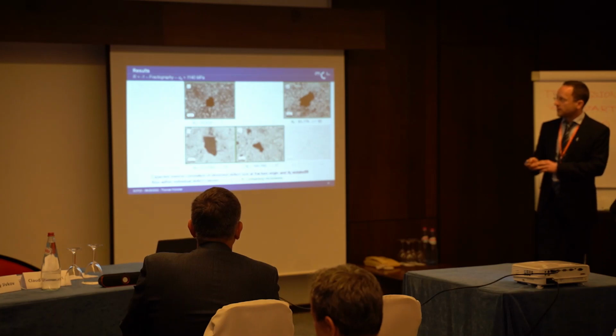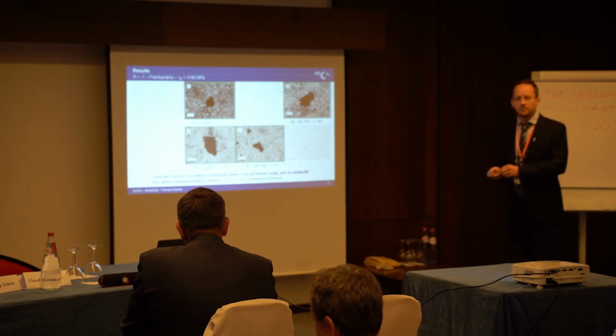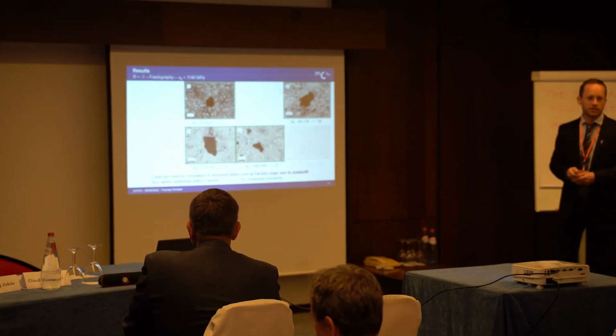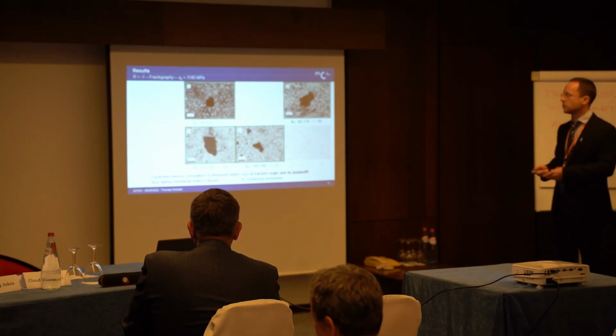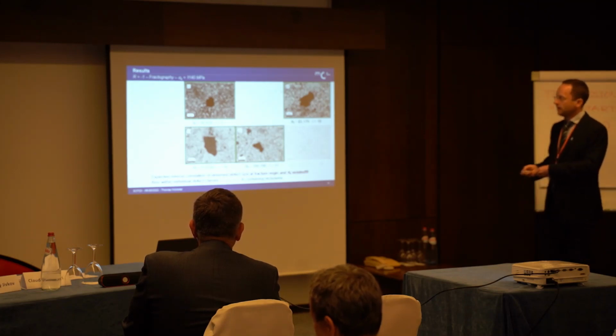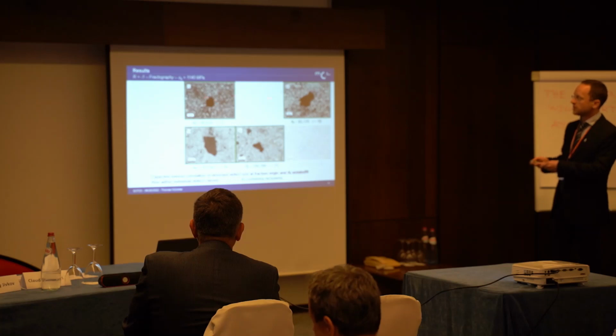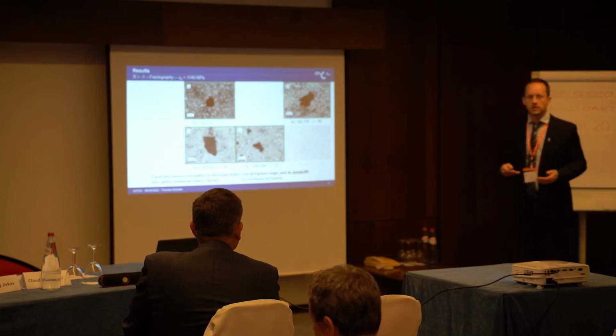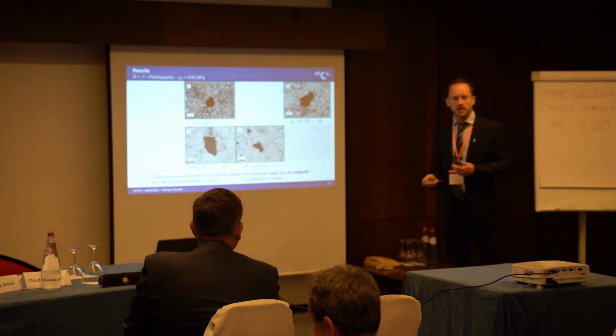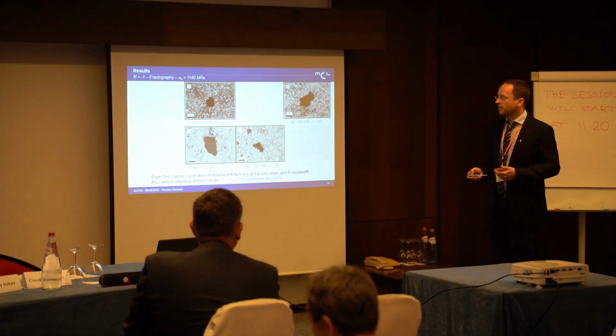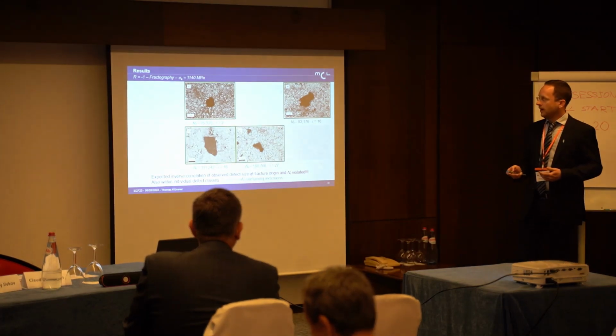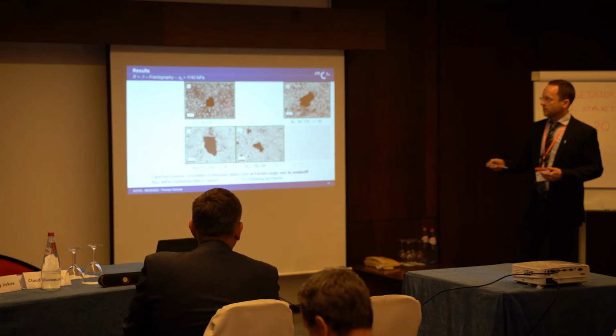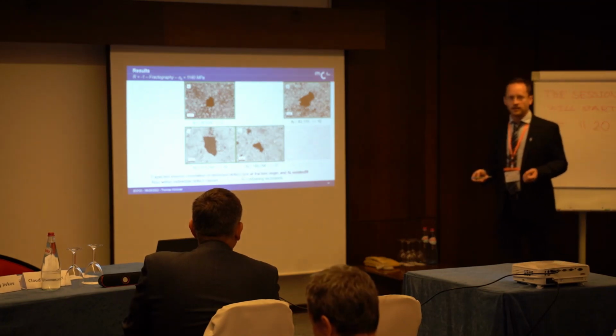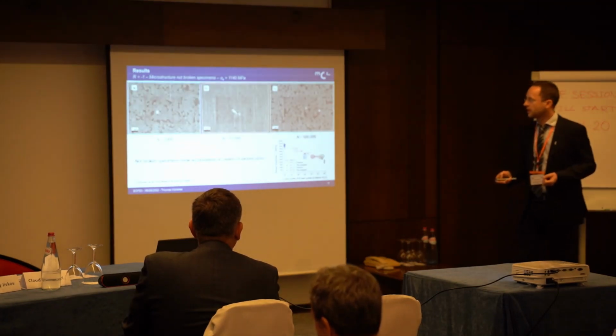And if you look at the next class of defects, which you could argue, okay, this has a different stress concentration factor because the chunk is smaller, the shape is different. Still here, you see the aluminum-containing inclusions, the size ranking doesn't really correspond to this expected inverse relation between NF and size. So I think the coalescence of pores that emerge here plays a role, and I can maybe convince you by showing you this here.